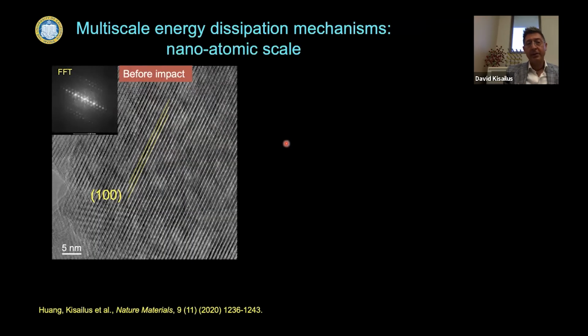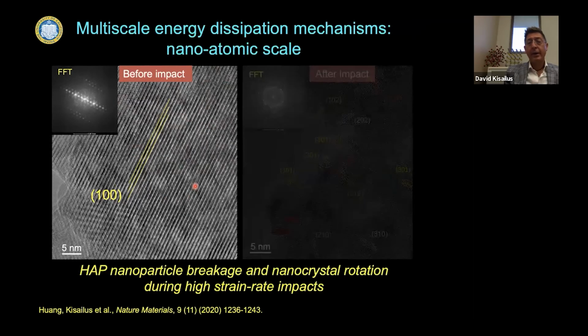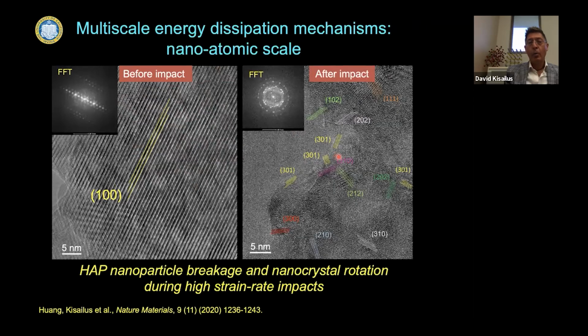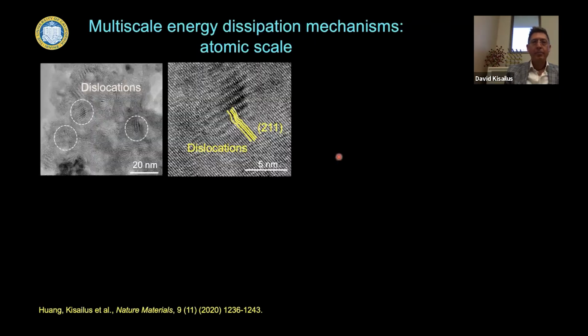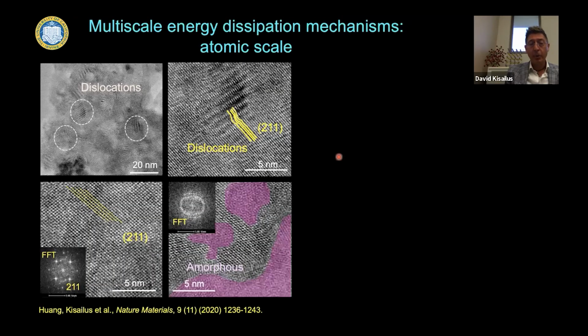At what I call the atomic scale, we actually see something else happening. So again, this is the intact particle before impact. After impact, you can actually see where those, I call them Lego blocks, those mesocrystals, are stacked on one another. Those low angle grain boundaries are more prone to being fractured and will therefore dissipate energy upon fracture. And in addition to that, we do see some dislocations forming, as well as some amorphization during these high strain rate impacts. Again, additional sources of toughening.